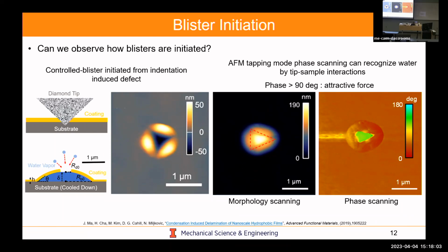This is environmental AFM, where this is our nano indentation. It's more micro indentation in this case. And by looking at phase imaging, you could actually see that water will form inside the blister and it'll fill it up. And then actually it'll cause this deformation to grow bigger and bigger.